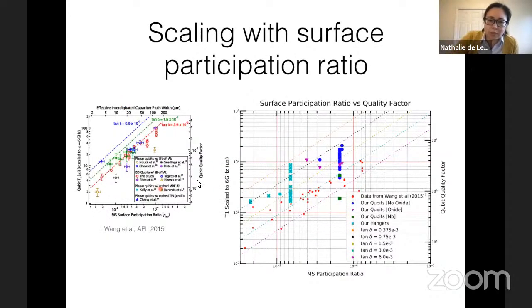And then just to probe that a little more systematically and in more detail, what we can do is take this nice plot that Chen Wang put together in Rob Schoelkopf's group of many different qubits with different surface participation ratios and their quality factor, and then plot our data on top of it. So these blue points here are all of our tantalum qubits, and these little blue crosses are these resonators. So we're now trying to sweep the surface participation ratio. And we indeed do find that we're on a scaling that's around a factor of 5 better than what was previously reported in the literature. So that's very exciting, and what we're doing is using this now as a basis for further improvements.